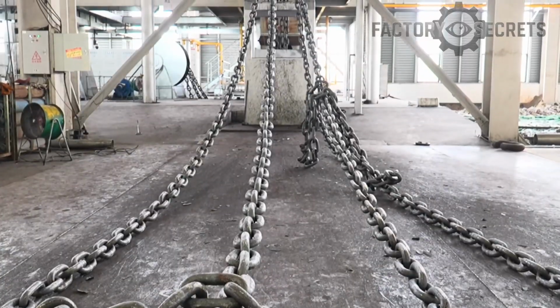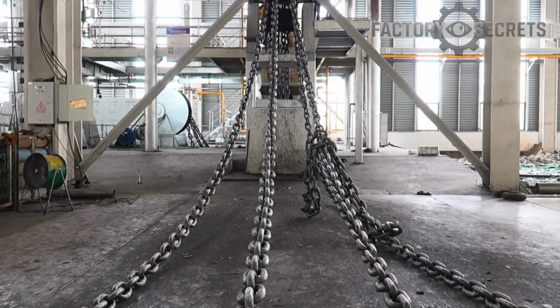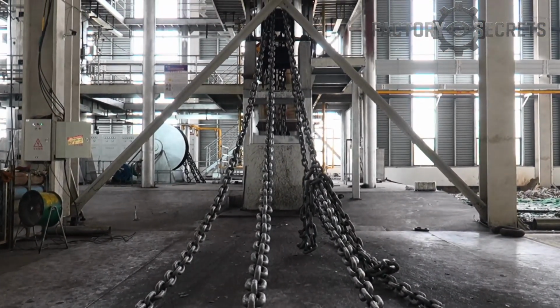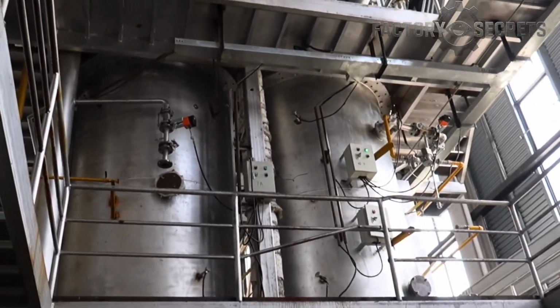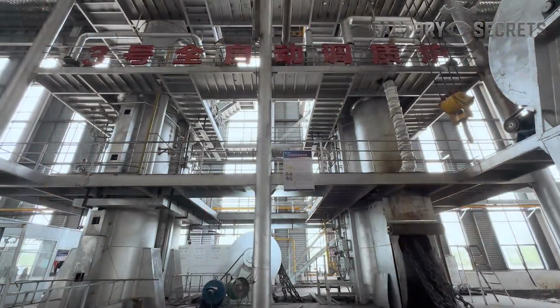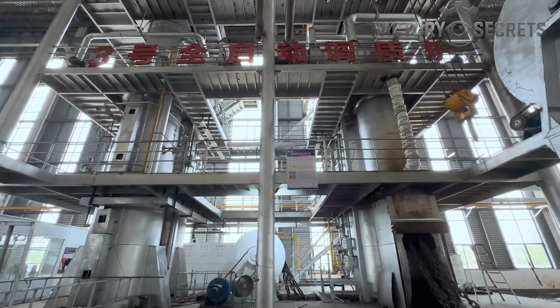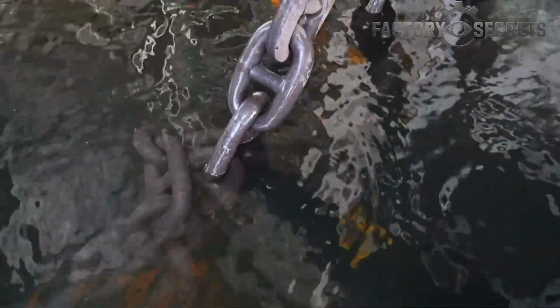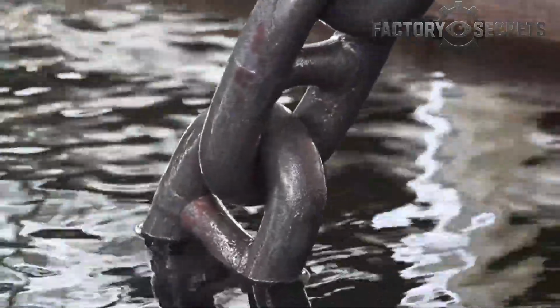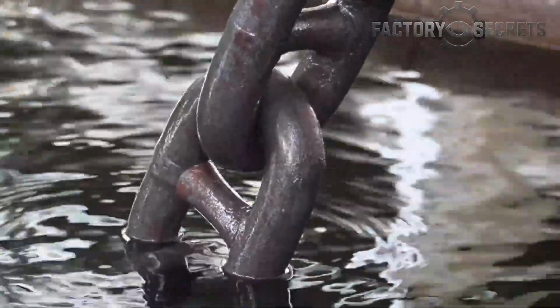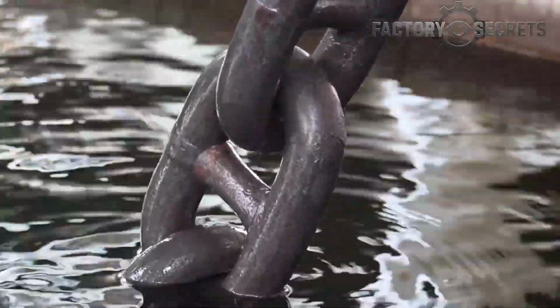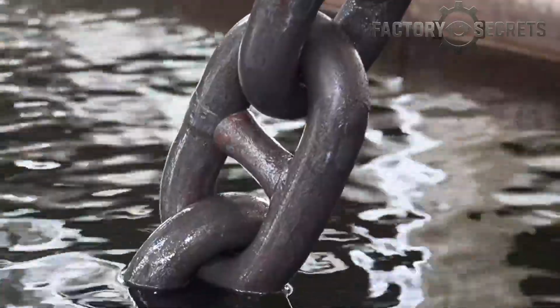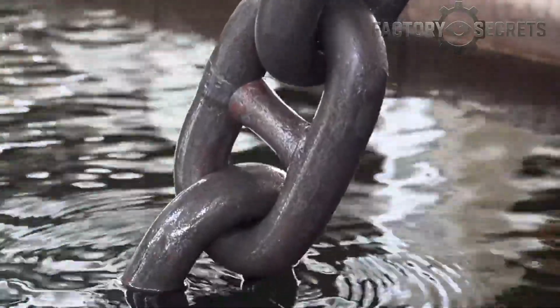From the welding floor, the chains are moved to a solution bath, submerged in a water-based chemical mixture. This step serves multiple purposes: cleaning surface oxide from the welding and heating processes and preparing the steel for the rigorous testing that comes next. It's a deceptively simple-looking stage, but every step in this process exists for a reason. The solution bath ensures that what's being tested next is pure steel performance, not contaminated by scale or surface debris.